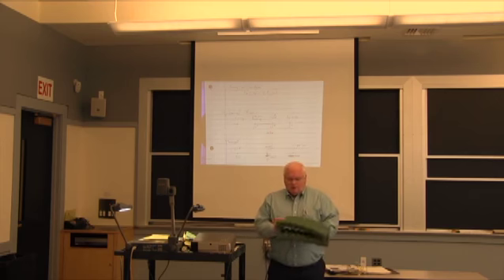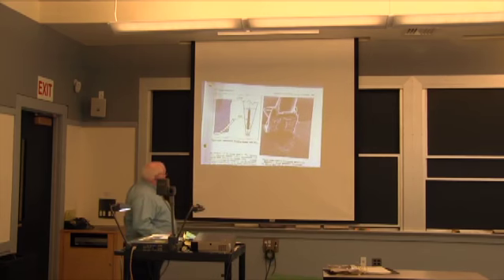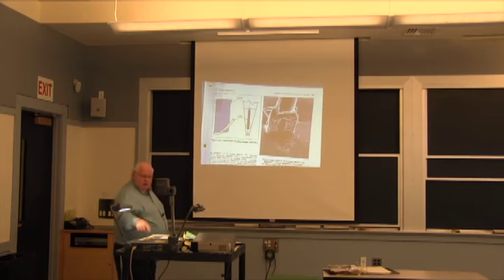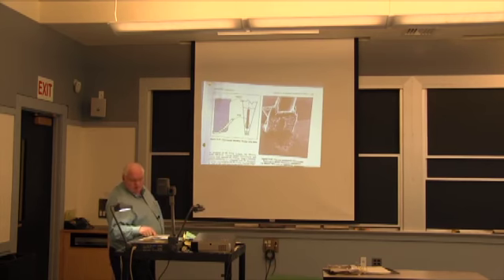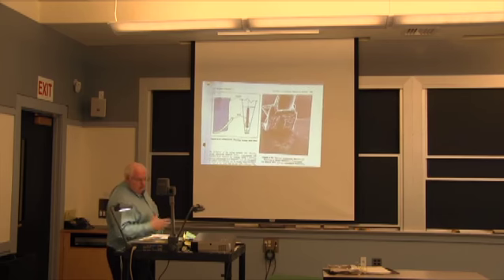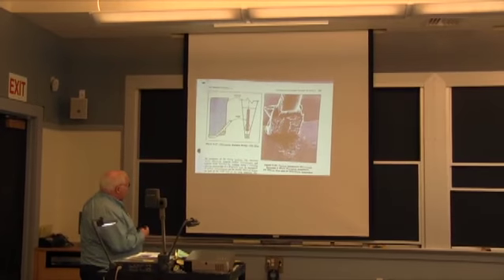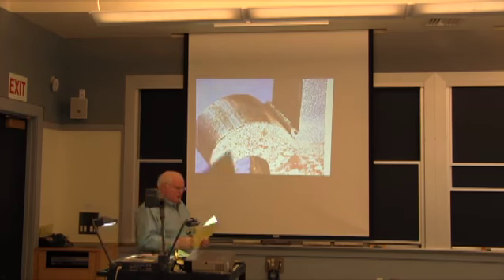You're essentially getting impact loads to deform these things. And remember, the two things: you've got to get rid of surface contamination, and you've got to get rid of surface roughness. So what we're going to try to do is break down by shear these interfaces, these little mountain peaks. I showed you this before, I'm pretty sure, which is an ultrasonic welding wedge bond. This is a little gold wire or whatever. Actually, it's aluminum silicon wire on an aluminum substrate. So it's maybe not for microelectronics. Basically you had a wire, and right in the center here, you just have a normal force squeezing on this, and you don't get the real bonding until you actually get shearing and break down those surface asperities and extrude out the impurities.